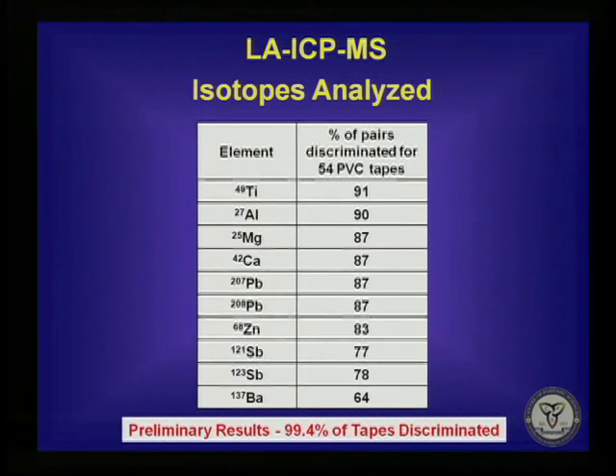We compared the results for the 54 tapes. The titanium was able to give discrimination of 91% of the tapes, aluminum 90%, magnesium, calcium, and lead 87%, zinc 83%, antimony 77 to 78%, and barium was 64%. Overall, we had a 99.4% discrimination based on the electrical tape backings.